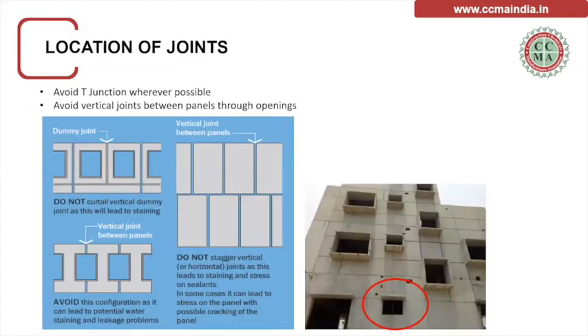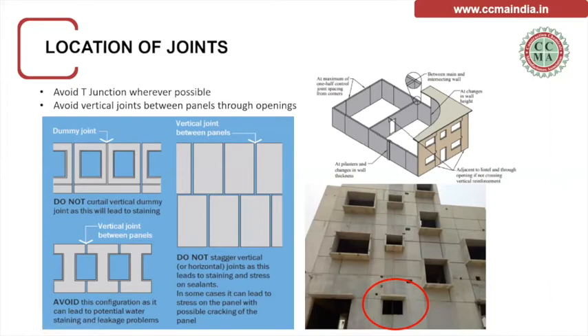Now, location of joints: one needs to avoid staggering vertical joints, as this would lead to staining and stress on the sealant. Second, one needs to avoid vertical joints between panels through openings. You see it is encircled in the red color. This type of joint location should be avoided. Again, the joint needs to be provided when the wall thickness changes or where there is a change in height.